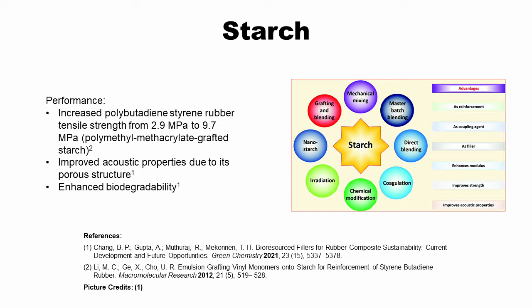As predicted, adding starch improves the structural properties of rubber significantly. Polybutadiene styrene rubber tensile strength increased upon the addition of polymethyl methacrylate grafted starch. In addition to this, due to its porous structure and ability to trap air, starch can improve polymer acoustic properties, allowing them to be used in many applications. Finally, being a preferred energy source of many microorganisms, starch additives improve the biodegradability of polymers.